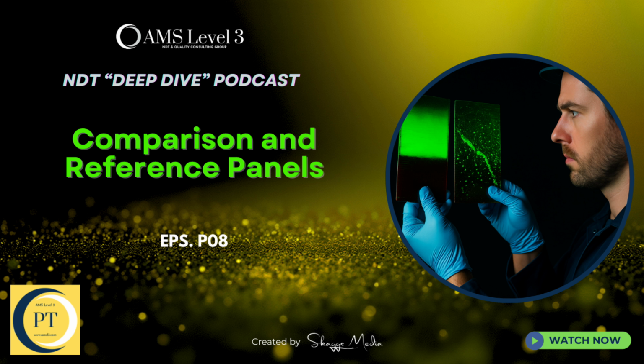Okay, that leads us to another specific type. The Liquid Penetrant System Monitor Panel, the PSM panel. Pratt & Whitney developed this one, right? What's its unique job? The PSM is really designed as a quick daily check for major system problems. Think sudden gross contamination or maybe the water temperature or pressure in your wash station went way off. It's a go-no-go indicator for big shifts. It typically has 5 crack centers made with hardness indentations to give different severity levels, plus a grit blasted area. That rough area helps you monitor the background fluorescence and how well your wash step is working.